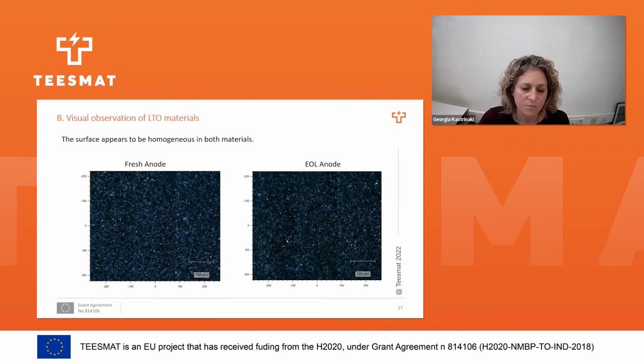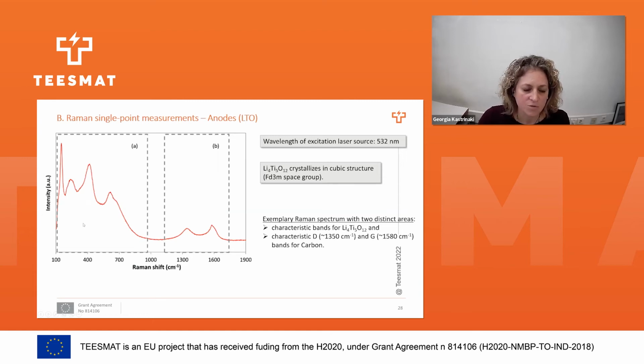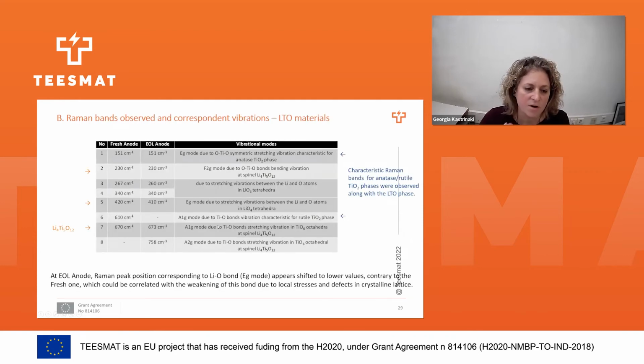Now, the second material that we observed was the anode, the LTO. Again, we had no differences in terms of morphology, let's say. Both materials are quite homogeneous. And again, we have the spectra of LTO. Again, we divide it in two regions. This is related to active carbon and this is to LTO. And these are the results that we obtained from the fresh and the cycled materials. What we see again is that we have small shiftings basically in these two vibration modes, the EG and the A1G again. This is related to the spinel structure of LTO.